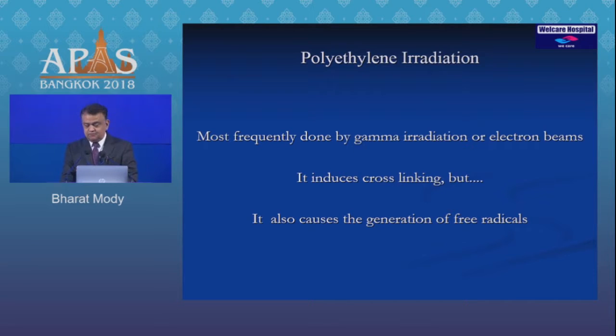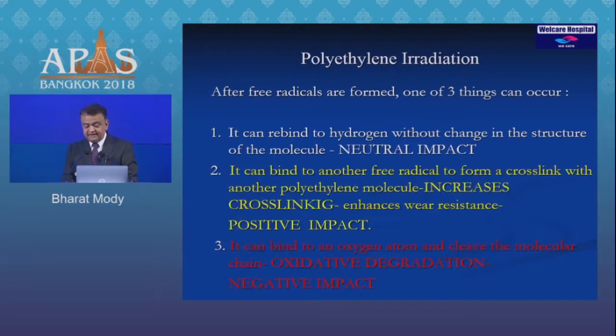So let's start this. Poly is irradiated either by gamma radiation or electron beams, and it induces cross-linking, which we'll see is a benefit, but it also causes the generation of free radicals. And what happens? Three things can happen when you have a free radical. It can recombine with hydrogen without changing the structure of the molecule, and that's a neutral impact. It can bind to another free radical to form a cross-link with another poly molecule. It increases cross-linking and enhances wear resistance. This is a positive impact. And it can bind with an oxygen atom and cleave the molecular chain. This causes oxidative degradation, and this is a negative impact.